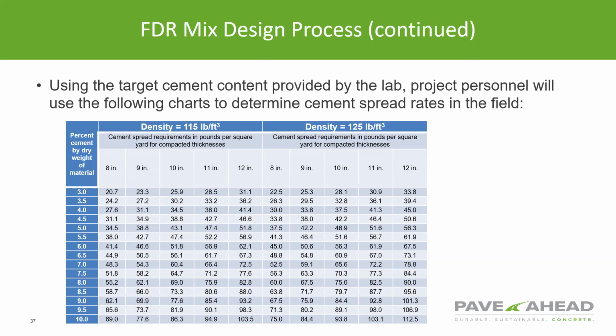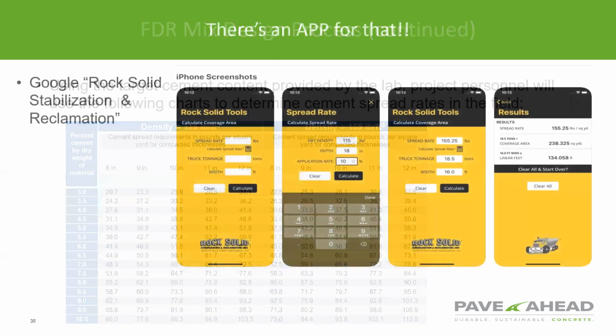when they do reclamation, generally speaking, the highway department on state highways, they don't take any of the subgrade materials below the asphalt and the base. So they stay in the granular materials, and they just use a flat 2% to stabilize those materials, and they found that that works very well. But in the normal situation, you're generally going into the subgrade material, so you're probably going to be in this range here. And then we'll look at this in a little bit more detail a little bit later.